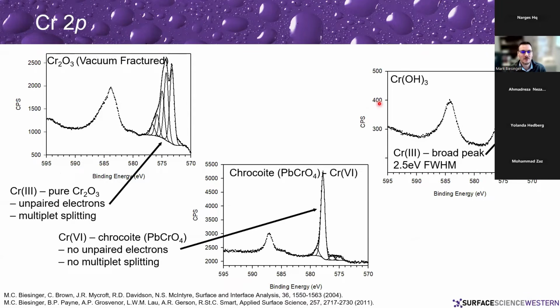And so if we look at a bunch of standard samples, we have our chromium 3 oxide up here, where we're able to model using a series of peaks that basically just mimic this peak shape. And so we have 5 peaks here of multiplet splitting. So the peak spacing between all these peaks is known, the areas of those peaks are known, and the full width half max of these peaks are known. And we're just using that as a model to model the shape of this structure. Something like chromium hydroxide over here has a broad single peak that we can model that shape with at a certain binding energy. Something like chromium 6 doesn't have any multiplet splitting, so we have a nice sharp peak at a known binding energy that we can use.